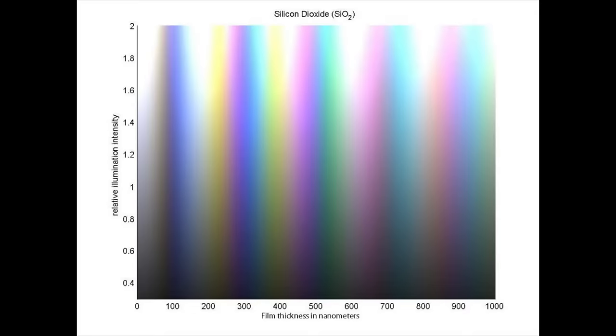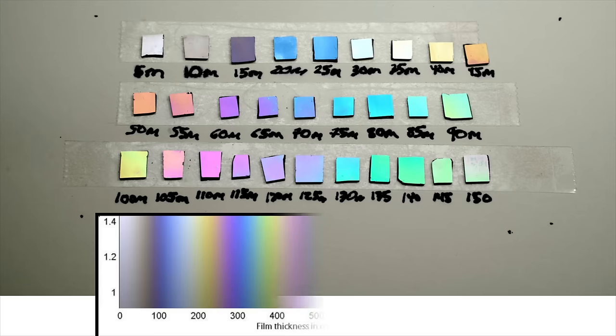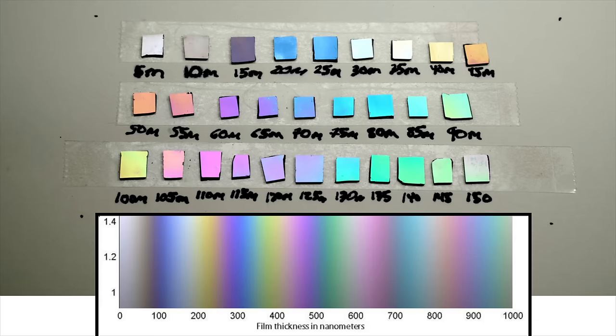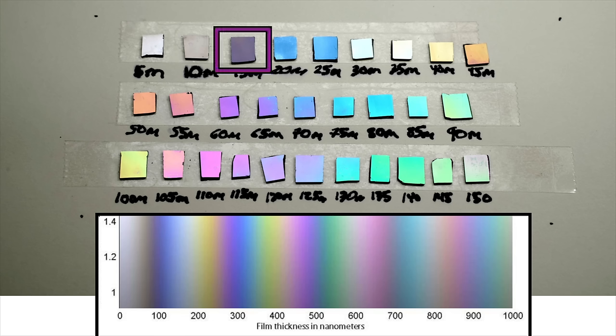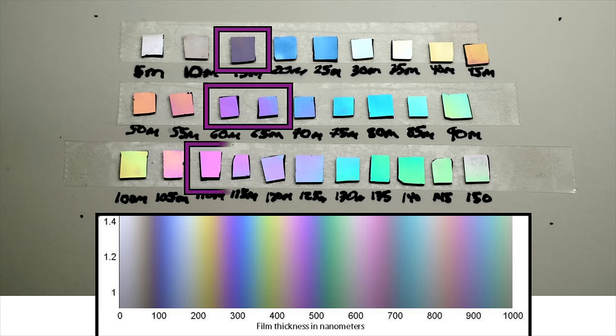This is a chart showing the colors that we can expect to see from thin layers of silicon dioxide on silicon wafers. As you can see, the colors on the chart match pretty well with our experimental results. The only thing that is a little bit off is that our spectrum seems to stretch out over time. You can see in the top row that the colors cycle relatively quickly, but by the time we get to the bottom, it takes 20 or 30 nanometers for the colors to change.